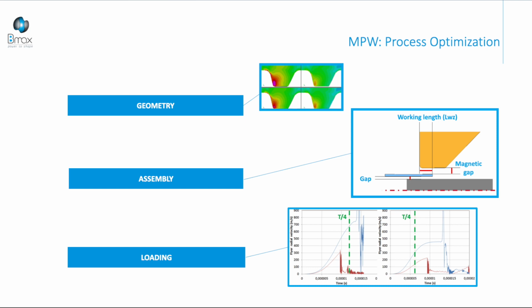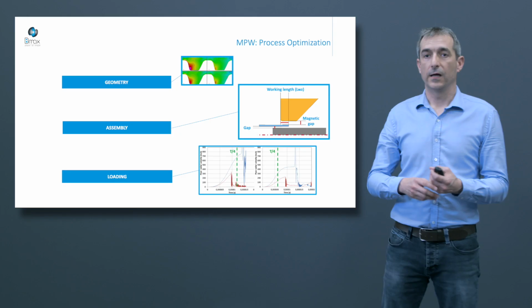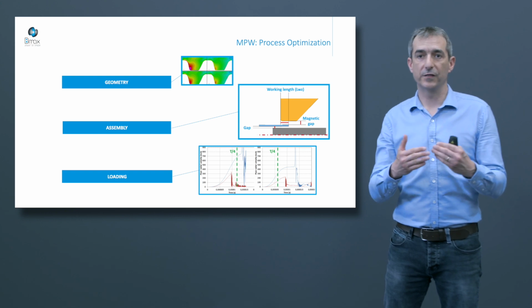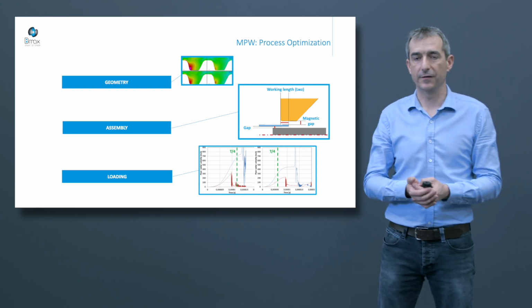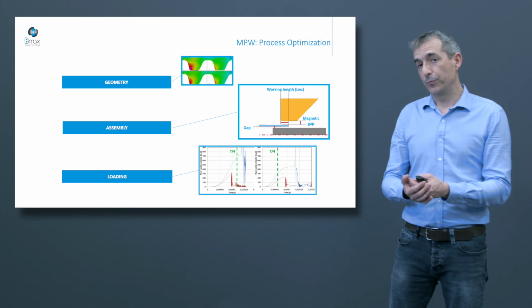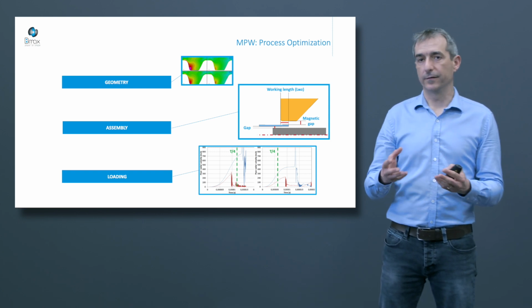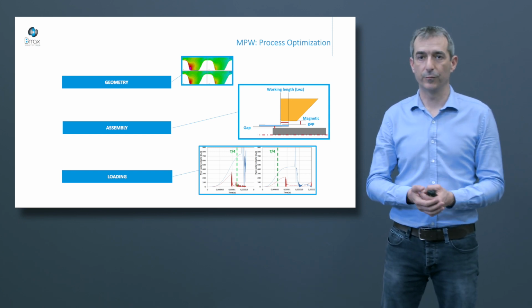Regarding the geometry, we can optimize the coil section, for example, to increase the current density and the Lorentz force applied locally on the flyer. And we can change the parent part geometry to maximize or to change the angle at the impact. The second point to optimize is the assembly. Again, working length and the gap between the components.